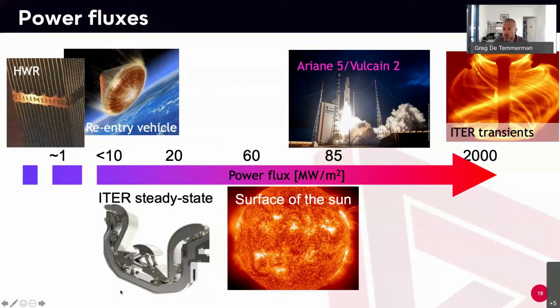And for ITER, ITER is a project of about 20 billion euros. But the pieces inside are going to have to live for about 10 years. So you have to deal with that heat for very long durations. And during instabilities, there is basically no equivalent. So the only equivalence you can find is if you think of a black smoker, eruptions under the sea. But you typically don't have to deal with that.